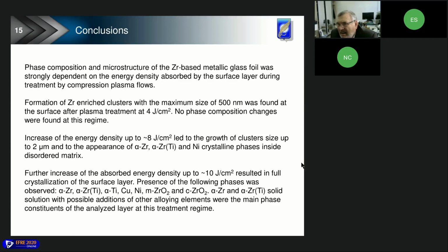During plasma effect, we receive at lower energy, we see local areas of melting, but very small. So during X-ray analysis, we do not see any crystallization. At higher energy, of course, melting of the surface occurred during plasma impact. So the surface layer was melted and crystallized at high energy.